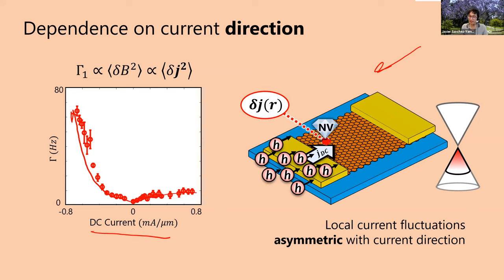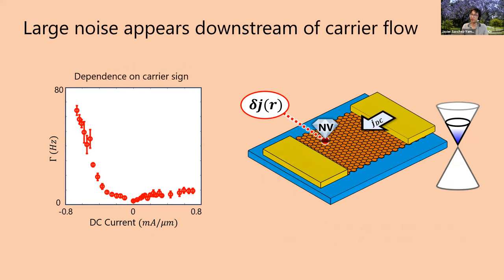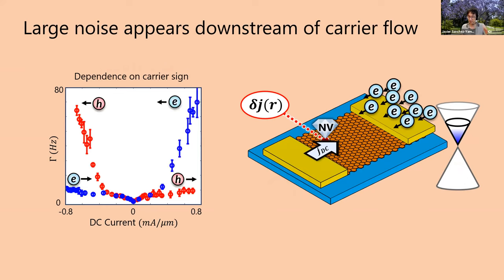But what's cool is that we can actually flip the sign of the carriers by changing the doping from holes to electrons, okay? And we see that the profile flips sign. Okay, so now we get large noise when we put the current in the other direction. And so the important thing here is not the direction of the electrical current, but the direction of carriers, or the direction of momentum flow in our system. That's gonna determine where the noise is gonna be the largest.